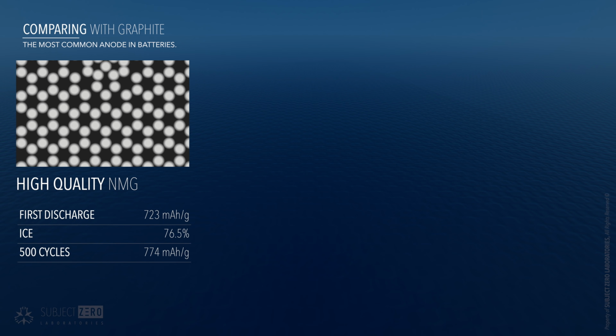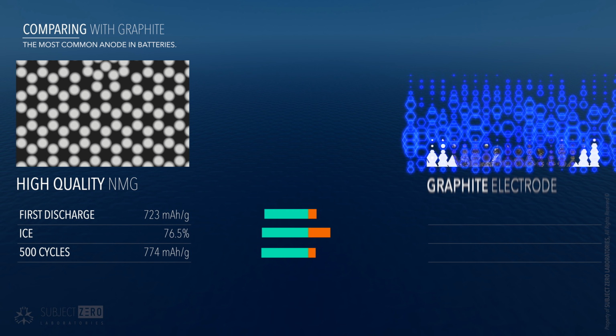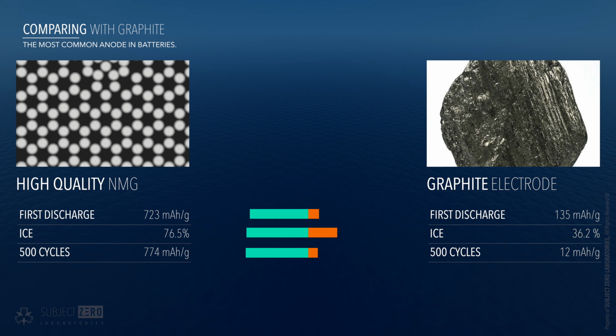Now, if you were kind of lost with these numbers, let me clear things up by introducing graphite electrode numbers. Given the same experiment, on its first cycle, it held a discharge capacity of only 135 mAh per gram. And after 500 cycles, it dropped more than 10 times, or to 12 mAh per gram. In this experiment, high-quality NMG was 64.5 times better than conventional graphite after 500 cycles.